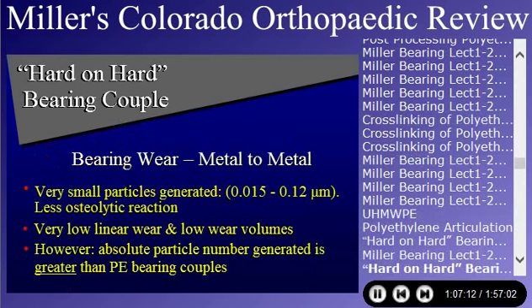You've got to remember this, is that metal bearings, ceramic bearings do generate particles, but they're very, very small. And it is thought because these particles are so small, they elicit less of an osteolytic reaction. And it is thought that particles 0.2 microns or above are what cause osteolysis. Anything below 0.2 may not generate that osteolytic reaction as much. And what you need to remember is that these hard on hard bearing couples generate actually more absolute debris particles than the soft bearings, because they're so small you can't see them, but the absolute number is actually increased. What you do see, though, is very low linear wear rates and very low wear volumes, but the particles are so small the absolute number is actually higher.